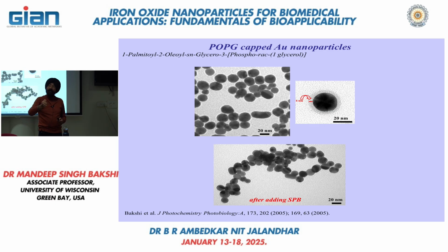We just added them in combination of the pulmonary surfactant suspension, and then we tried to disperse them, and we saw after the mixing, and we got the TEM image, and we saw that the pulmonary surfactant, they created the bilayer around each gold nanoparticle.